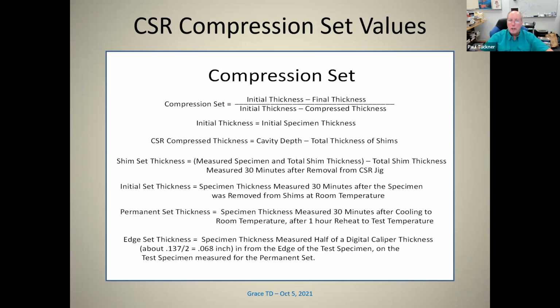The original one, the first one I did, I call the shim set. The shim set is where you remove the specimen from the CSR jig in contact with the shims, then measure the thickness of both the shims and the test specimen, and subtract the thickness of the shims to determine the compressed thickness of the specimen in contact with the shims. Then you separate the shims from the specimen and note the adhesion, because that's important.